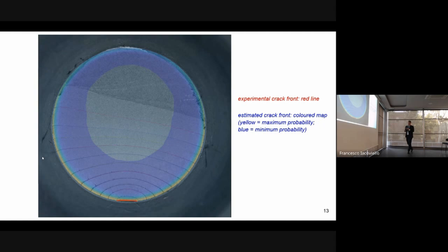Here, I'm going to show the results, and I'm almost done with the presentation. You can see on the bottom the fracture surface. We highlighted the benchmark crack front. The experimental crack fronts are highlighted for different crack depth by the red line, while the contour plot shows the estimate performed by our algorithm. You can see with the yellow color the region where there is the highest probability of the surface of being cracked somehow, and with blue, the region that has the lowest probability of being cracked.